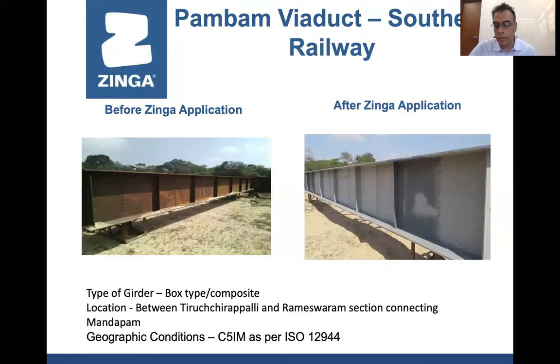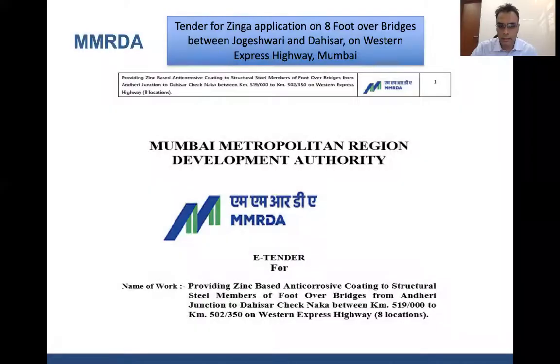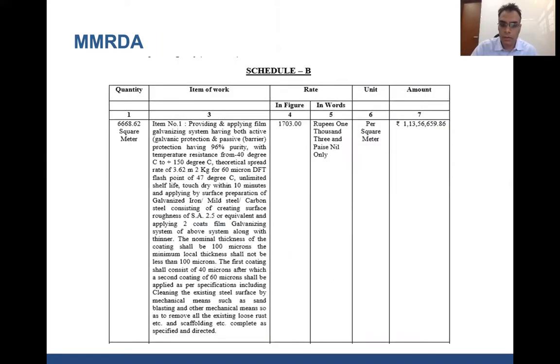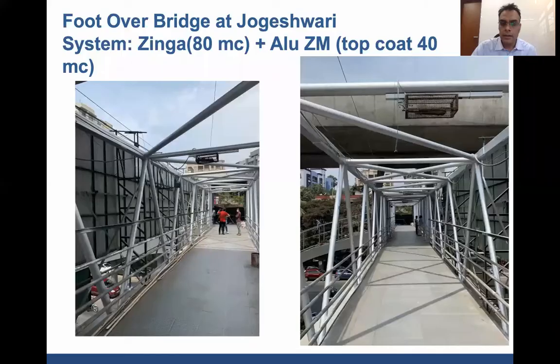Again, the corrosion environment as per ISO 12944 is C5, which is extremely corrosive, which means it's over water. So there also we applied Zinga. This has also been approved by MMRDA, and we have applied Zinga on 8 foot-over bridges in Mumbai from Jogeshwari to Dahisar. What we've done is, you can see that this is already there in the schedule of rates.